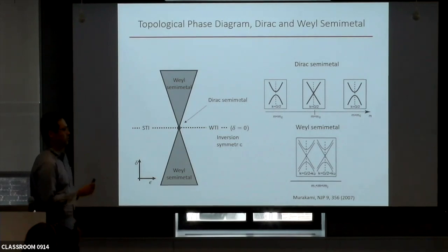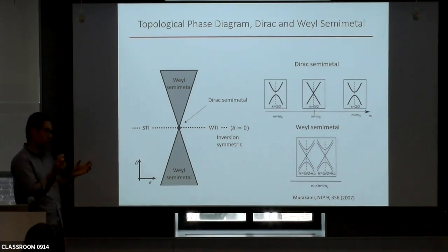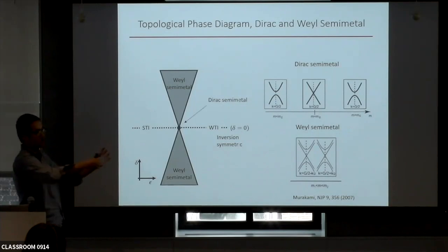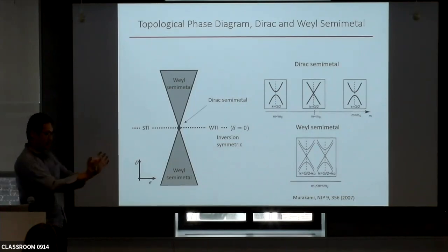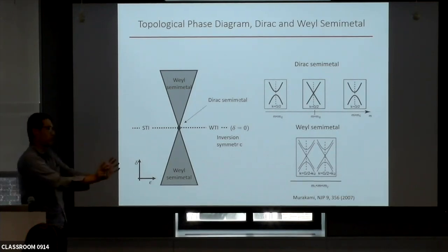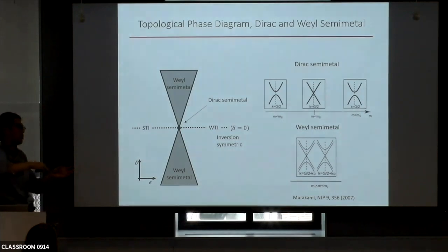We try to do that, and the answer is it failed. The way we do that is that you can actually measure the crystal without applying any strain, measuring R versus T, for example. And then when you put it on the device, because the device has all kinds of thermal contraction, you will naturally strain the crystal. But because now we can tune the strain, we can tune it back to the zero strain state by referring to the zero strain resistance versus temperature measurement.